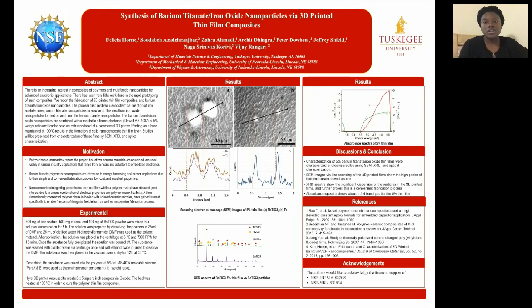multiferroic materials. So these nanoparticles were actually infused into a polymer, a two-part moldable silicone elastomer, part A and part B. So before we actually did that, the nanoparticles were synthesized. So the barium titanate was commercially purchased, and then the iron oxide nanoparticles were synthesized along with the barium titanate through iron acetate, urea, and DMF. And those were done through a sonochemical reaction for about 3 hours. And then from there, the particles went on to the centrifuge to be washed. And from there, once dry, we were able to get the particles.